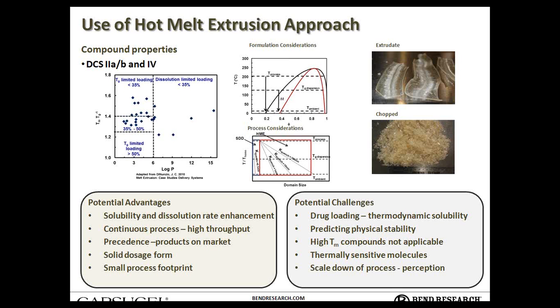Some of the challenges are, even more so than SDDs, drug loading, again, because we're trying to target low solubility actives having solubility in the polymer. Predicting physical stability can be challenged, because we're more towards a thermodynamic miscibility, setting things up at accelerated conditions to test how fast they fail. You're changing the phase diagram, and so it's harder to say what, at an ICH type stability condition, you could learn about storage at that condition from an accelerated one.